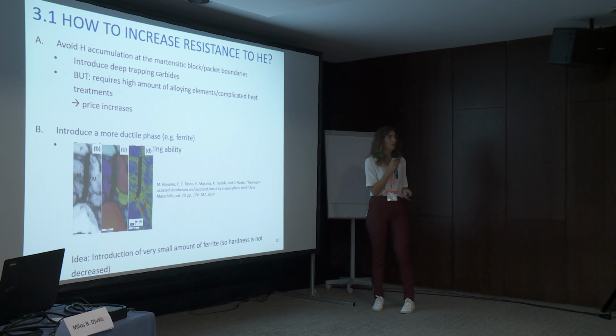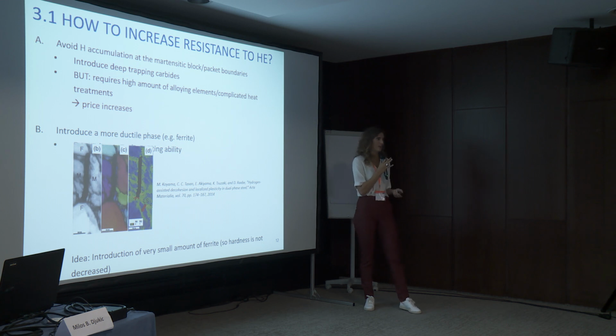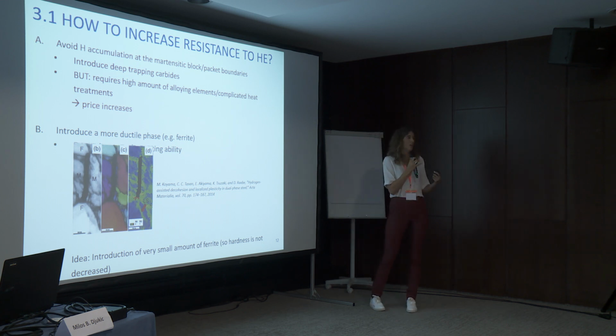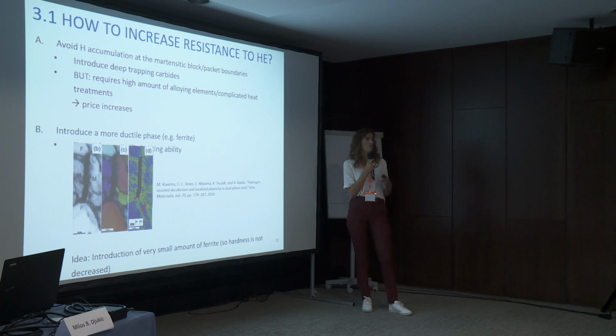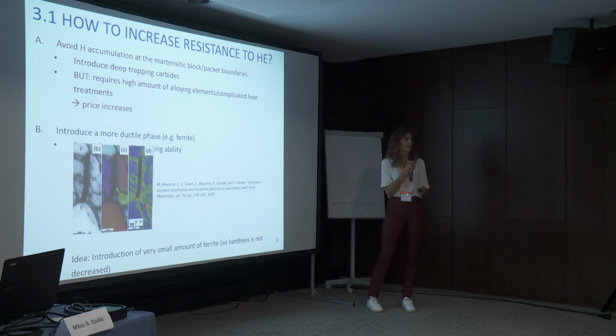A second way to do so is by introducing a more ductile phase. This is an example of Professor Koyama, and he showed that, in fact, ferrite has a high crack arresting ability. So by introducing a more ductile phase, we can really limit the crack propagation in this type of steels. However, martensitic steels are mostly used because they have a very high hardness, very high strength, and introducing a more ductile phase can really reduce the hardness. So the idea of my PhD was really to introduce very, very small amounts of ferrite to limit the decrease in hardness, but increase the mechanical behavior.